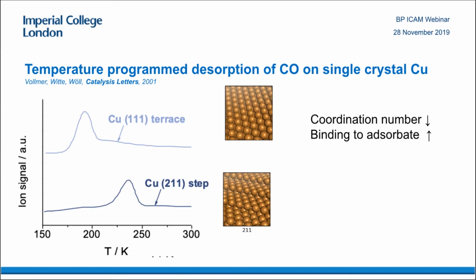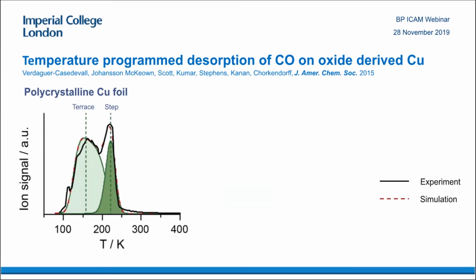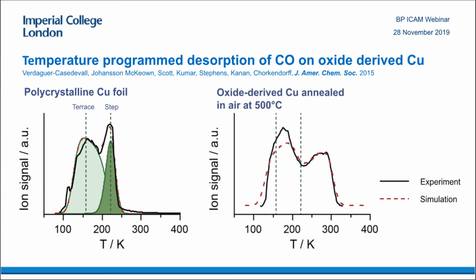So here's temperature programmed desorption of CO on the copper single crystals, both on the terrace, copper 111, which has very coordinated sites, and a copper step, which has a lot of undercoordinated sites. We then did the same kind of method on a polycrystalline copper. We saw the CO essentially desorbs at lower temperatures on the more coordinated sites, and the more undercoordinated sites, which tend to be a bit more reactive, it desorbs at higher temperatures. So then we did it on the oxide-derived copper.